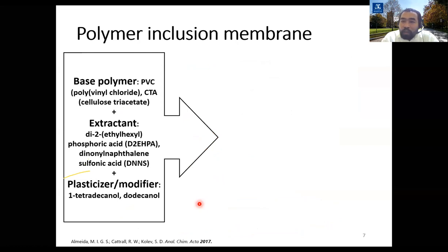So the polymer inclusion membrane is basically a new generation of liquid membranes, which consists basically of a polymer as the backbone. Commonly used is polyvinyl chloride or CTA, and an extractant, which can be an anionic or cationic exchanger. In this case, it can be di-(2-ethylhexyl) phosphoric acid or D2EHPA, depending on our target analytes. Sometimes a plasticizer or modifier can be added to plasticize our membrane.